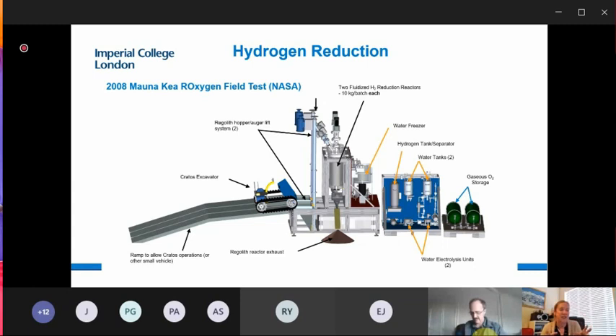Just over 10 years ago, there was a long period of research done by NASA that resulted in field trials in Hawaii. They tested two potential technologies. This is a diagram of one of them. And it worked. It scooped up soil and it produced oxygen with a yield of maybe a half to 1% of oxygen, depending on where you look. So there have been field scale tests of this. But in the last few years, we've seen a real push. This is a concept that's really received a lot more attention.